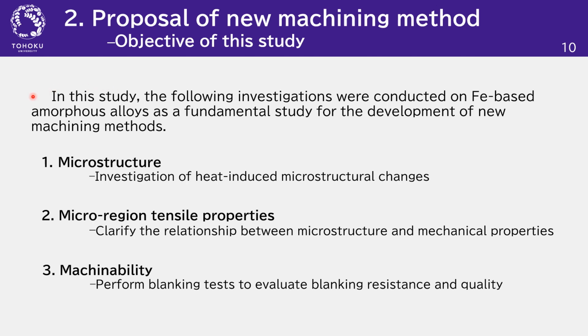In this study, the following investigations were conducted on Fe-based amorphous alloys as a fundamental study for the development of a new machining method. So we evaluated samples which were homogeneously annealed in order to discover a structure that is suitable for machining. First, we investigated the microstructural changes caused by thermal effect. Next, microtensile tests were conducted to clarify the relationship between microstructure and mechanical properties in the microregions. Finally, blanking tests were performed to evaluate blanking resistance and quality.